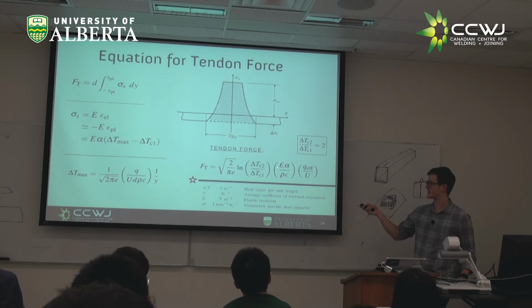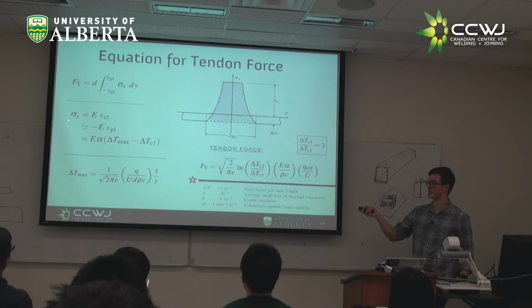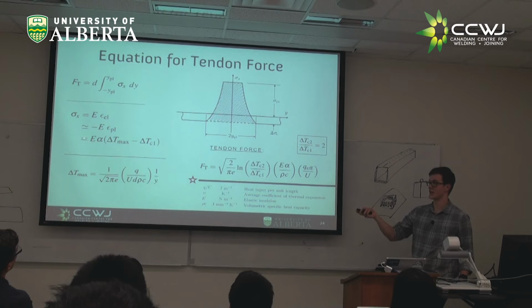So if we have the elastic modulus and we have our coefficient of thermal expansion, we can see those come from the fact that to get stress from elastic strain, we multiply by E. To get thermal strain or plastic strain from temperature, we multiply by alpha. So we have that E alpha. Now what about rho C? Rho C comes from the fact that we have this whole grouping here of Q over U rho C.